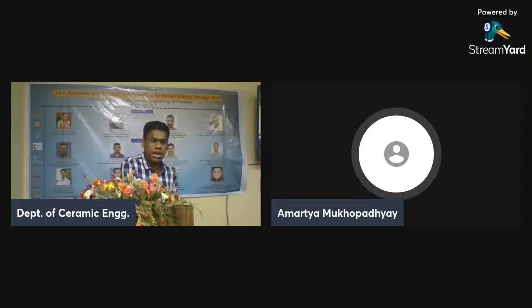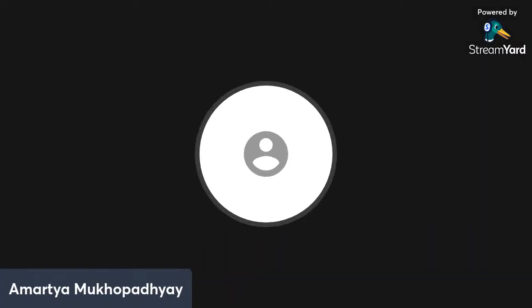Yeah, sorry, I did not stress upon it. Yeah, so I got your point. But if you refer to the composition, you can see there is nickel. So nickel is primarily the redox active transition metal ion. I can just put the composition in the chat box. Let me put it. So this is the composition. So you can see there is nickel in that, which is primarily the redox active ion, and also copper is in +2 state. So at high voltage, copper can undergo a +2 to +3 change in oxidation to take care of further sodium extraction.